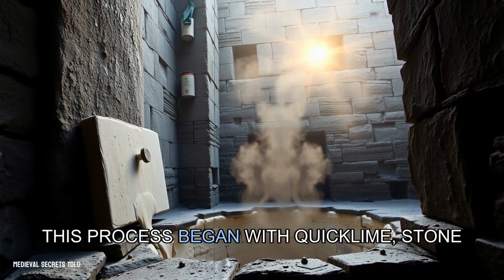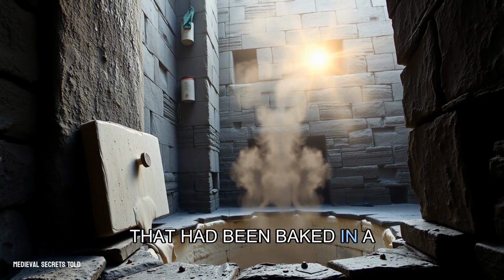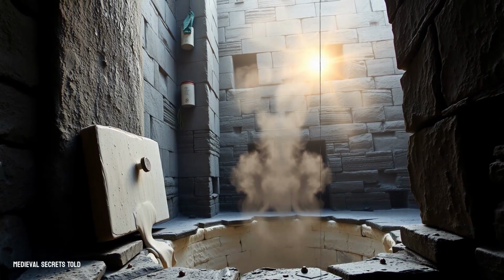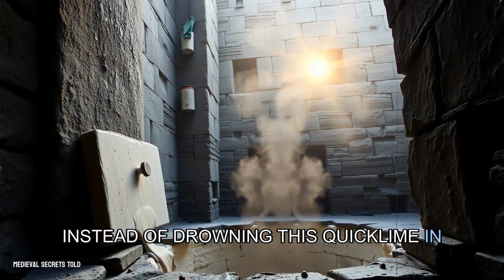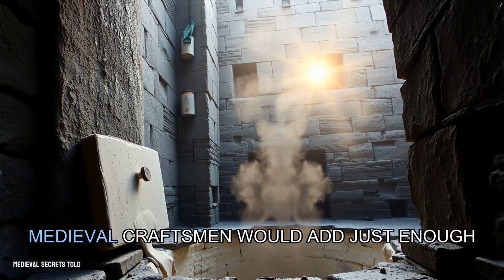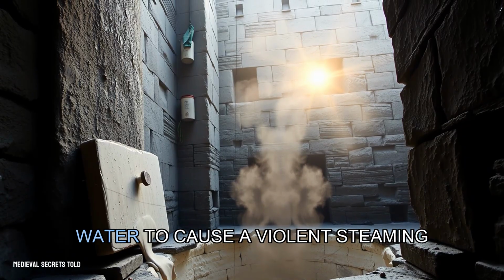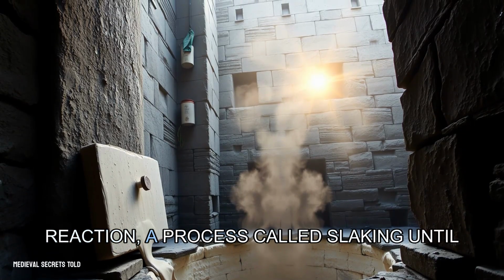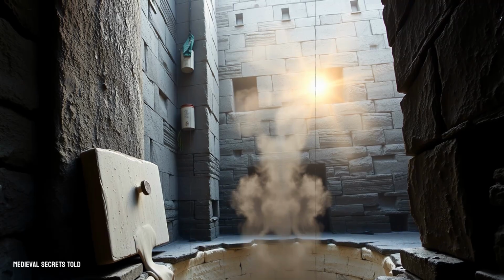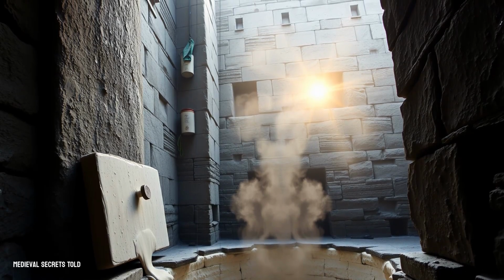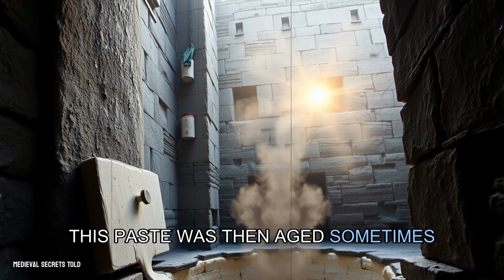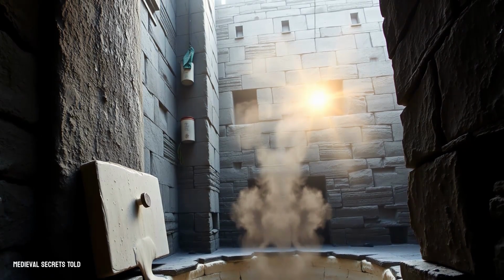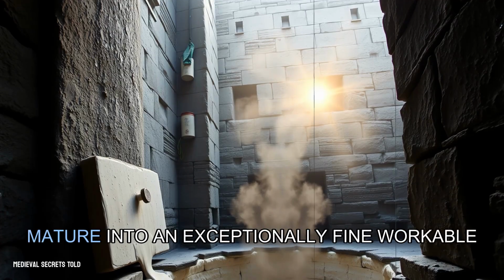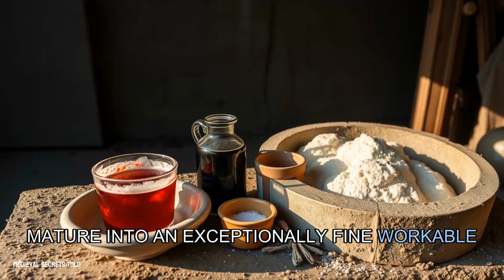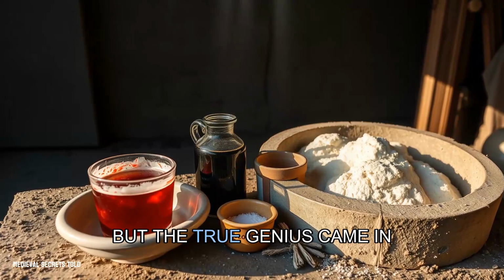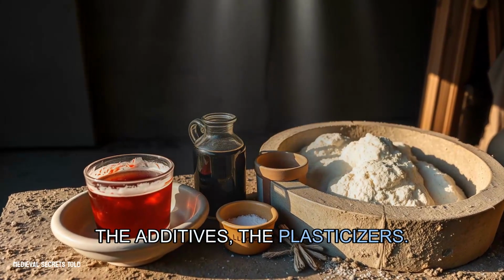This process began with quicklime, stone that had been baked in a kiln until it was highly reactive. Instead of drowning this quicklime in water to make a slurry, the medieval craftsman would add just enough water to cause a violent, steaming reaction, a process called slaking, until it formed a thick, putty-like paste. This paste was then aged, sometimes for months or even years, in a pit. This aging allowed the lime to mature into an exceptionally fine, workable material. But the true genius came in the additives, the plasticizers.